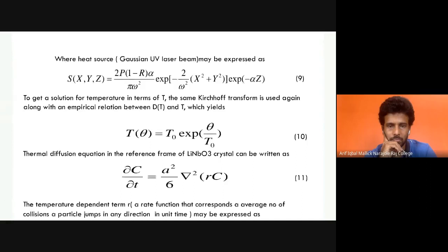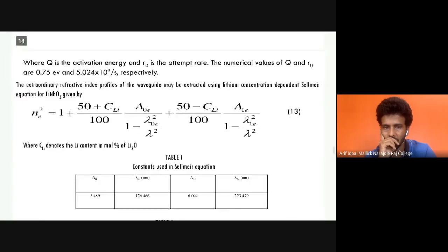Most researchers assume alpha is a constant, but in our model, we introduce alpha as a temperature dependent term, which is able to explain the formation of the UV written waveguide. Finally, using the diffusion equation, written in equation 11, we obtain the concentration profile. Then using the Sellmeier equation, written in equation 13, we obtain the refractive index profile.